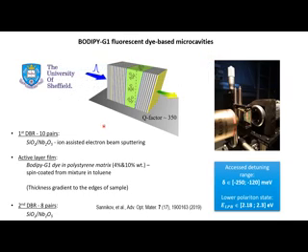So our material system is the following. It is the lambda-half microcavity, strongly coupled microcavity, with two DBRs basically, and the organic material is the following: BODIPY-G1 dye in a dispersive polystyrene matrix film, in two different concentrations. I will tell a little bit more about that.